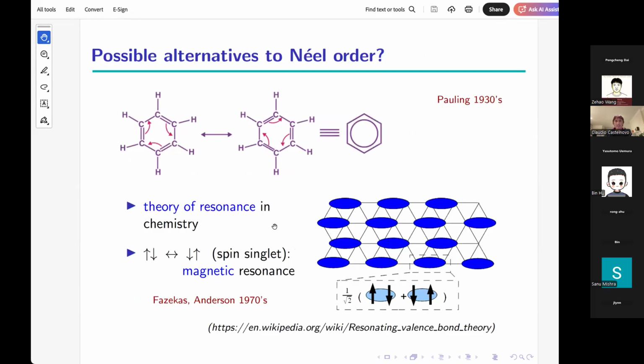And the idea of an RVB liquid dates back to the 1970s, where Fazekas and Anderson, in the context of superconductivity, in fact, were thinking of a possible alternative to Néel order. Néel order is what happens when you have antiferromagnetically coupled magnetic moments, and the best thing you can do if you are on a bipartite lattice is to put them anti-aligned with their neighbors, and you form an ordered pattern. An ordered pattern through which transport is really difficult to occur because it would leave behind domain walls that cost a lot of energy. They were interested in easy transport, and in the context of superconductivity,